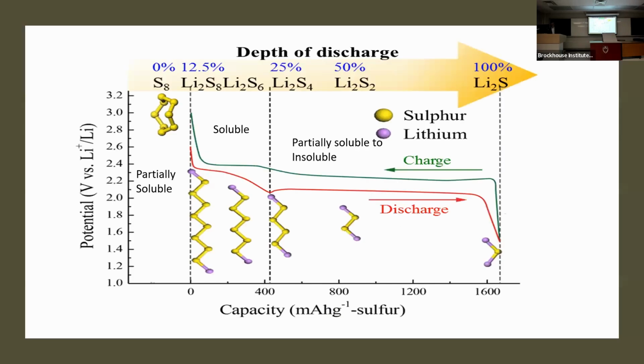Yeah. But what are the problems? Let me highlight some of the problems. It's a very complex chemistry compared to lithium-ion batteries, which is an intercalation from one structure to the other structure through a liquid electrolyte, through a membrane which is flooded with liquid electrolyte. The membrane is simply nothing more than a polymer. Yeah, sometimes reinforced with oxides like silica. Sulfur is partially soluble in those liquid electrolytes. And when it reacts with lithium, it forms polysulfides in a polymeric chain, which is fully soluble in the liquid electrolyte.